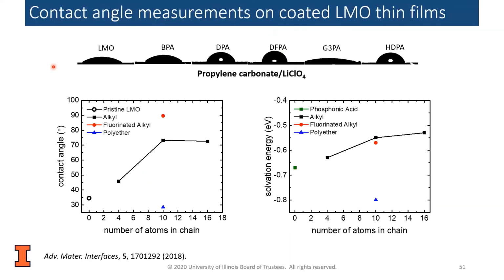So here's some comparisons of the contact angle measurements with the solvation energy. So these are some examples of some common solvent electrolyte compositions. And so as I mentioned, metal oxides will have a hydrophilic surface. And so we want to study the effect of wetting. Okay, so you can see that the propylene carbonate wets very well. And as you can see, it has the lowest solvation energy.